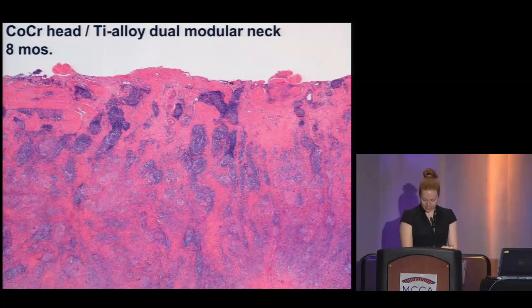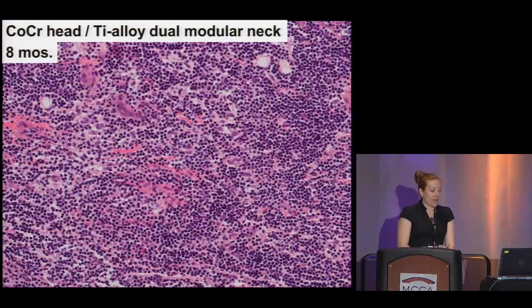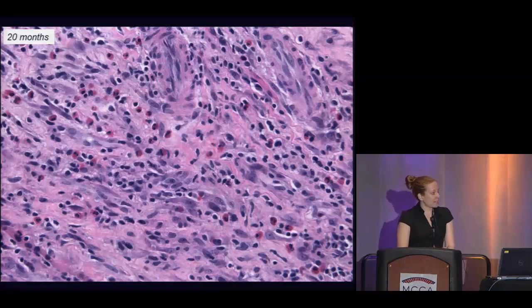Histologically, in the periprosthetic tissues, the joint capsule typically demonstrated a marked perivascular lymphocytic infiltrate. This is similar to the response seen in metal-on-metal devices. At a higher magnification, we can appreciate this intense lymphocytic infiltration. In some cases, the lymphocytes were accompanied by plasmacytes and eosinophils.